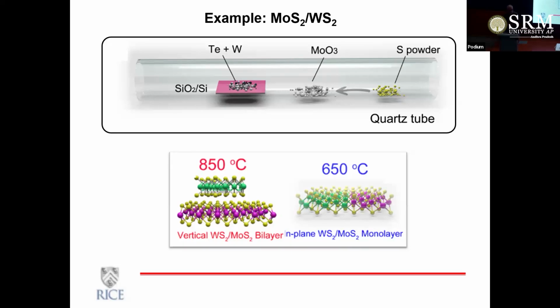Again, we do a lot of vapor phase growth, and together they grow. Depending on the phase stabilities and phase diagrams, you could find a condition where they actually separate completely, segregate, right? So that might be one way of doing this. Again, it's a lot of trial and error and optimization. And today, people are actually trying to do this in a more controlled, rational way to be able to create the exact stack that you need.